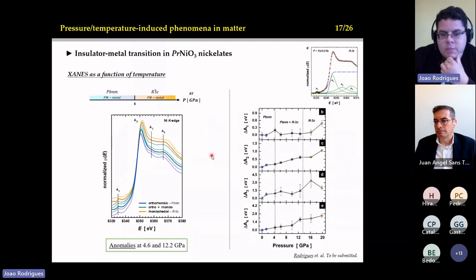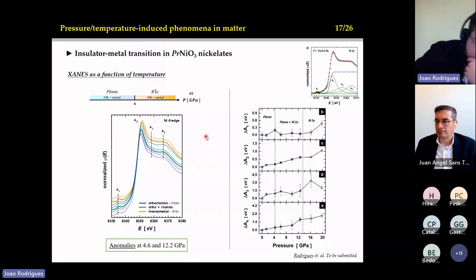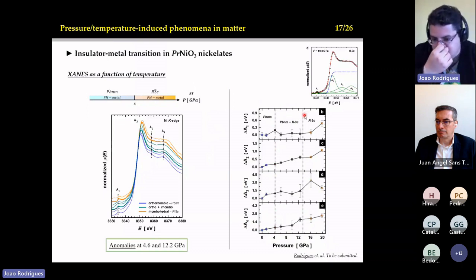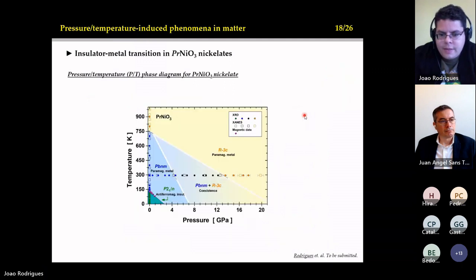And then we did the same with absorption at the BM23 beamline, and also comparing with the data from diffraction, we really confirm the transitions and also the coexistence. So the main message here is, if you want to really understand locally, in the short range, the long range order transition in this material, we need to use the facilities available at these two beamlines.